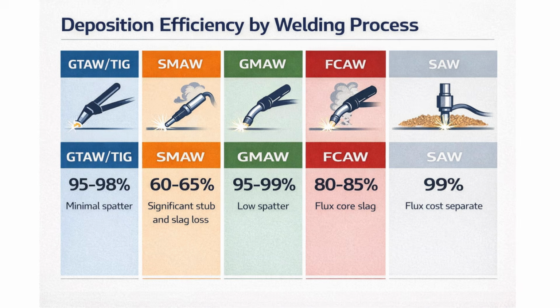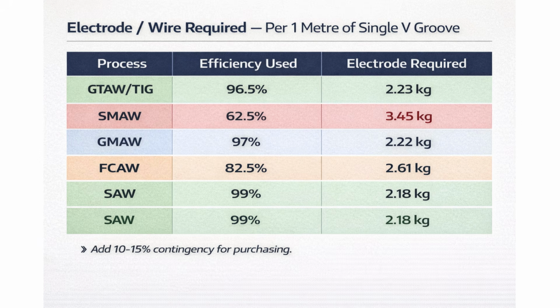Deposition efficiency reference table. To find actual electrode required, divide the weld deposit weight by the deposition efficiency. For SMAW at 62.5% efficiency, 2.155 divided by 0.625 equals approximately 3.45 kilograms of electrode. For GMAW at 97%, 2.155 divided by 0.97 equals 2.22 kilograms of wire. For GTAW at 96.5%, 2.155 divided by 0.965 equals 2.23 kilograms. And SAW at 99%, just 2.18 kilograms.